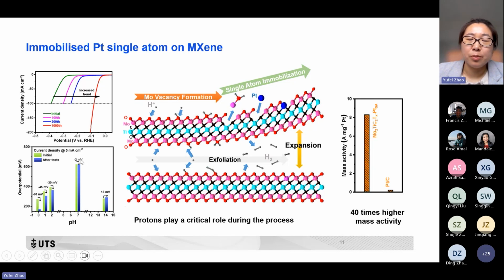In the neutral conditions, we can see performance maintains almost no change. In the alkaline conditions, the performance decreased a little bit, but the decreased performance may be attributed to the deactivation of the MXene in alkaline conditions, or the interactions between the positively charged potassium with the negatively charged oxygen termination here. But from this experiment, we can see that with the change of the pH, the performance decreased accordingly. The increasing trend decreased, and from neutral to alkaline, the performance decreased a little bit. That means the protons in the electrolyte indeed play quite an important role for the exfoliation of the MXene.